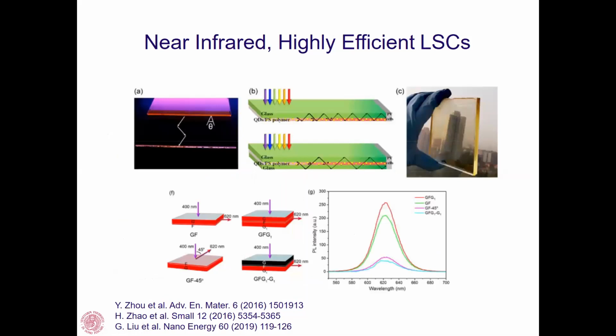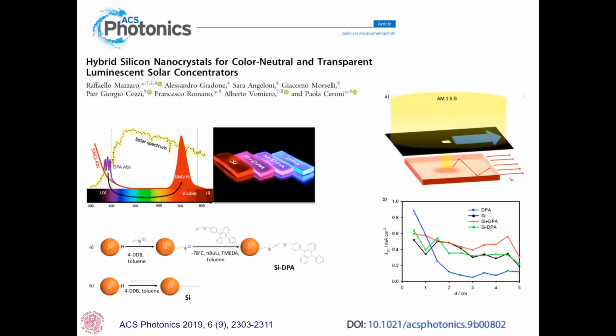And then we arranged different structures for luminescent solar concentrators in which either polymer or sandwich glass can act as a light transporter. Let me give a couple of examples before concluding. One is about the possibility to use silicon nanocrystals, which emit in the close to near infrared region, linked with absorbance in the UV region, so you can obtain transparent or semi-transparent luminescent concentrators, which also use the UV radiation. So you can broaden the range of radiation which can be used.